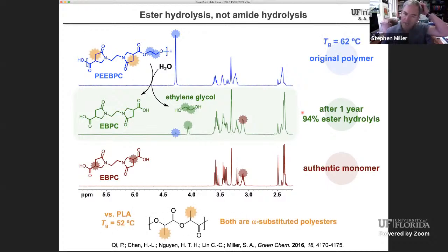We have a little bit of an idea as to why this might happen. If you are an organic chemist and have worked with a lot of solvents, you might appreciate or have used N-methylpyrrolidone, which kind of looks like that part of this polymer. And you'll note that N-methylpyrrolidone is a water miscible organic solvent, so it's obviously very hydrophilic. And so we think that that particular portion of the backbone of the polymer is fairly hydrophilic. It draws water in, causing the gelation.